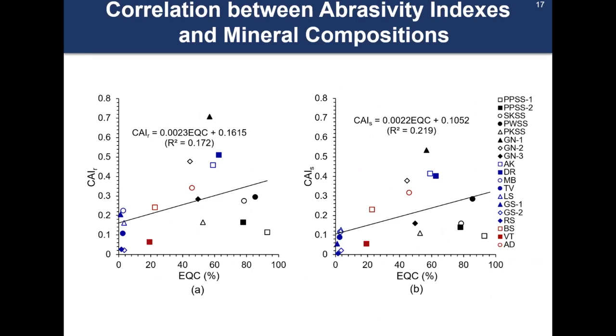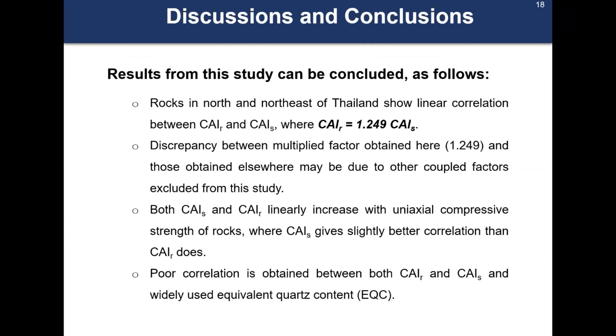Correlation between abrasivity indexes and mineral compositions. Graph A shows correlation between CAIR and EQC, and B shows correlation between CAIS and EQC. Explain that correlation coefficients are 0.172 for rough surface and 0.219 for smooth surface. So, poor correlations are obtained. Results from this study can be concluded as follows.